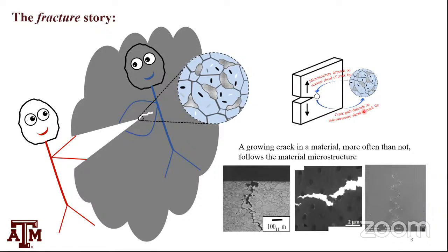Well, more often than not, we know from a material science perspective that a crack in the material follows the microstructure. So microstructure does have many roles. It also makes the crack grow in a certain way. If we look at it this way, oh, it is helping the bad guy, because there are features in the microstructure that allow the crack to grow easily. But then there are also features in the microstructure that trap the crack or move it around.